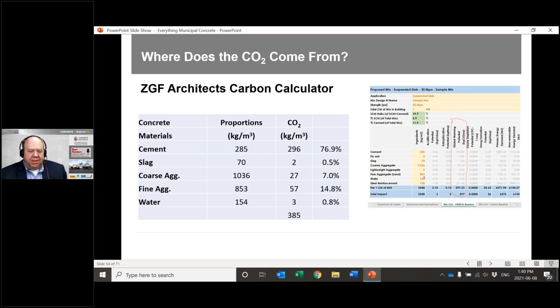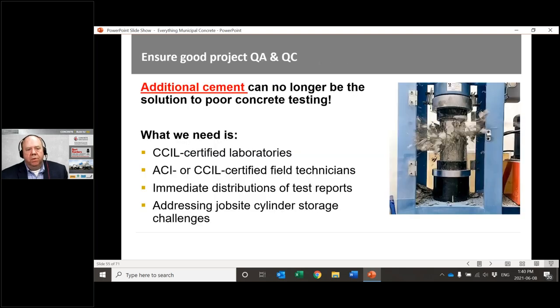So going back to this table, really what it comes down to is how can we use the lowest carbon concrete or cement possible. So the first thing that we do when we look at this is immediately get rid of this GU cement and replace it with GUL. There's a 10% reduction right off the bat. So we'll start walking through some of the steps that we can take out on job sites.